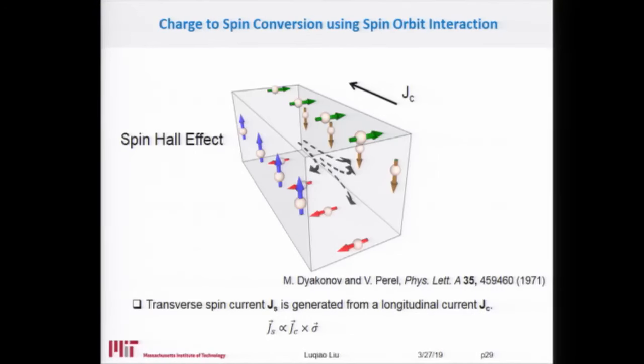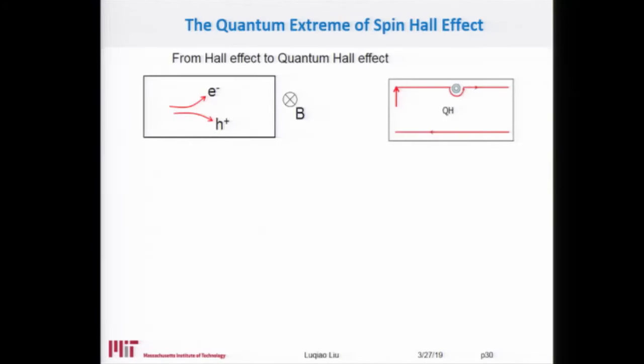The reason is, as I discussed, in today's talk we only focus on spin Hall effect for magnetic switching. Spin Hall effect is when you apply a longitudinal charge current, and then you generate some transverse or vertical spin current. This is an intrinsic property of materials. You may naturally ask, what material has the strongest spin Hall effect? If you want very efficient spin current generation, what material should we look into? We can make some hand-waving argument that topological insulator is probably the material with the strongest spin Hall effect.